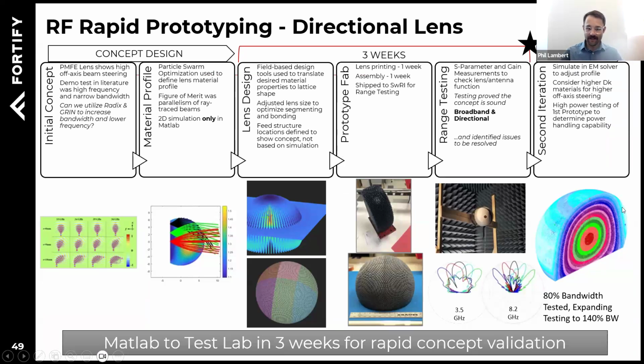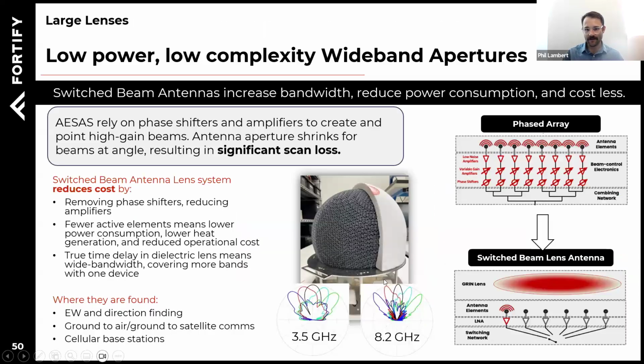And so we designed a 13-inch diameter lens with an organization called Southwest Research Institute. And they did some computational design to create this large lens. Fortify segmented it into 6 pieces, which you can see here. Here's one piece printed here. This was assembled and then attached to a device at the bottom here to mount 5 waveguide feeds. And then that was fed to generate a high gain lens for low power, low complexity wideband apertures.